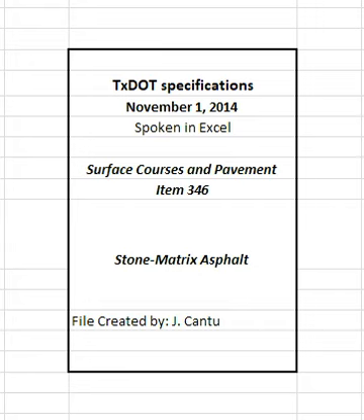4.4.2.2.7 Approval of JMF2. The engineer will approve JMF2 within 1 working day if the mixture meets the requirements in Table 4 and the gradation meets the master grading limits shown in Table 7. The asphalt binder content established for JMF2 is not required to be within any tolerance of the optimum asphalt binder content established for JMF1, however, mixture produced using JMF2 must meet the VMA requirements shown in Table 7.